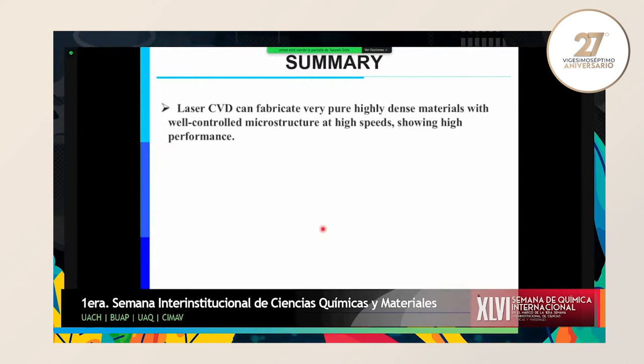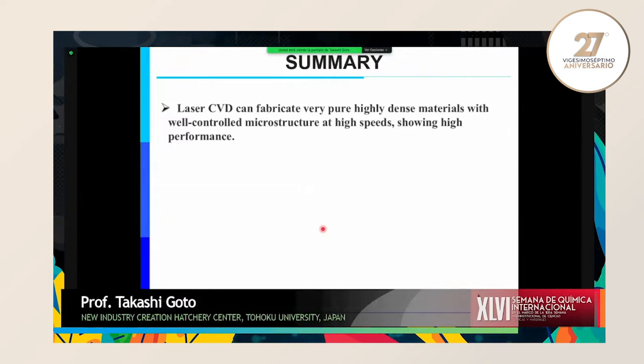So it is not easy to make very faceted, very oriented, very crystalline material. If it is a very thin, nanometer-order film, that is okay, because not many nanoparticles form in the gas phase. But if you want to make a several-micrometer or somewhat thick material, MOCVD is very difficult for making very faceted films. It is likely to become agglomerated nanoparticles or poorly oriented films.